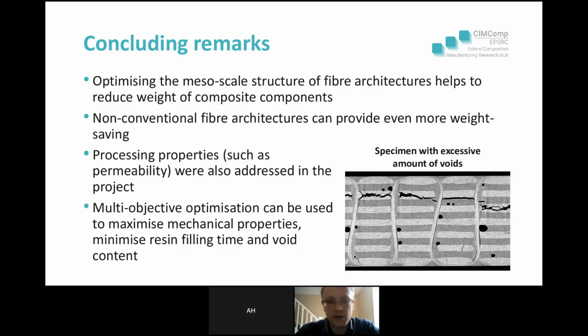What I didn't cover in this presentation is optimization of processing properties, such as permeability. Because you can optimize the mechanical properties, but you can arrive at an architecture which is very difficult to impregnate with resin, or when impregnated, will have a high void content.